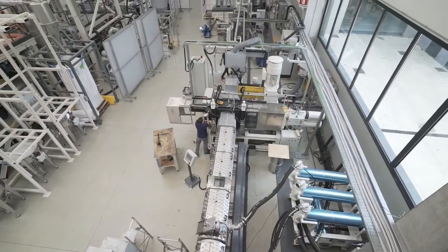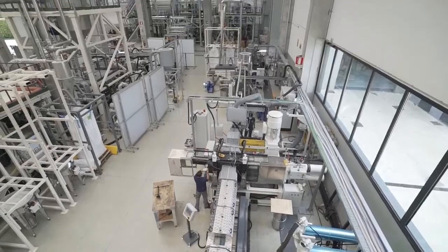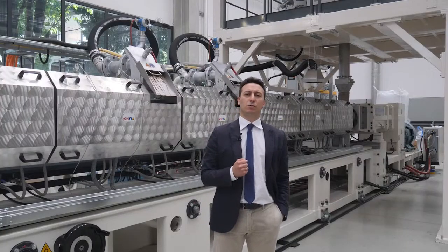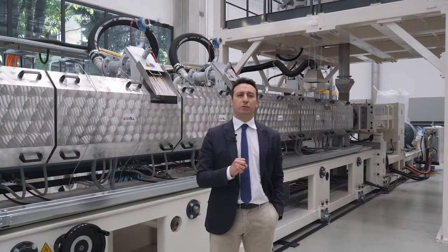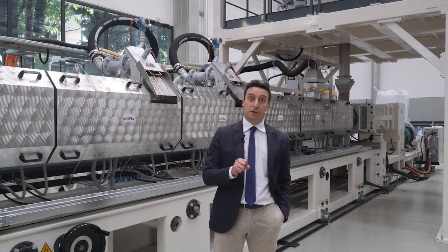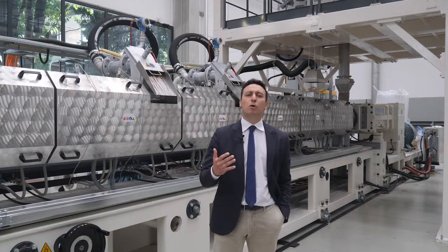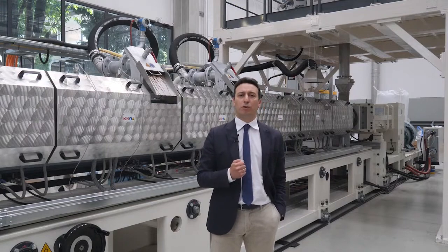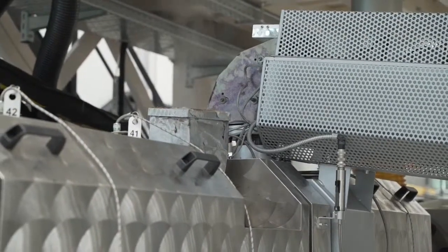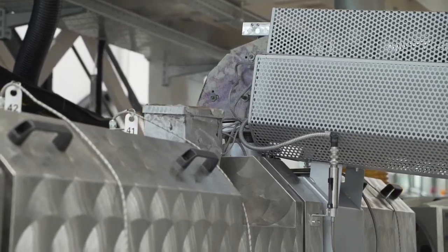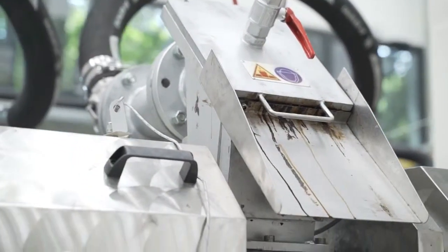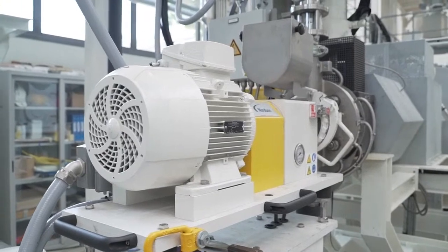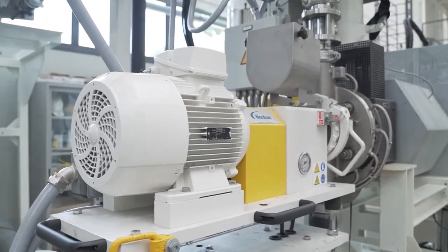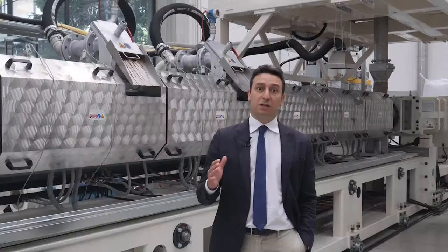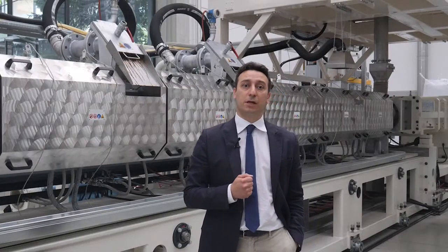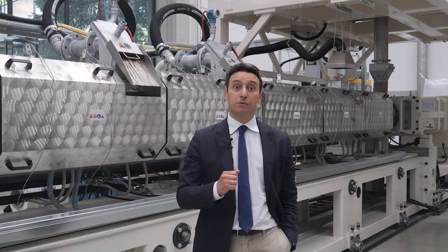The secondary twin screw extruder performs an additional degassing stage for the extraction of the VOC generated by the previous filtration, in which solid contaminants such as paper and wood can burn and generate undesired subproducts. Moreover, the two-stage degassing process dramatically reduces ink and solvent contents. The extruded melt can be fed to the pelletizing die head, or to reach further quality levels, it is possible to install an additional filtration stage to reach 30-40 microns severity.